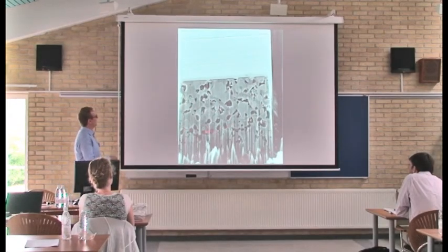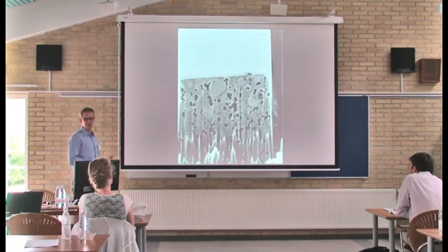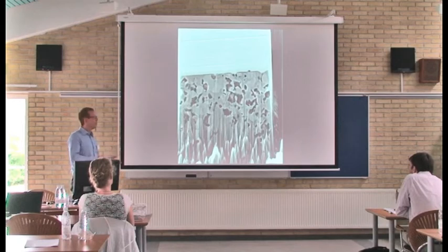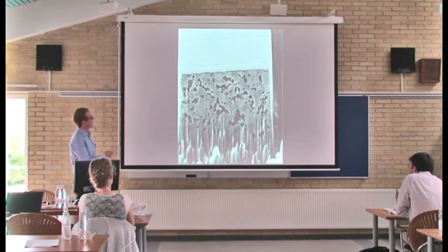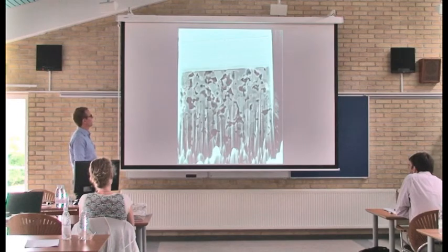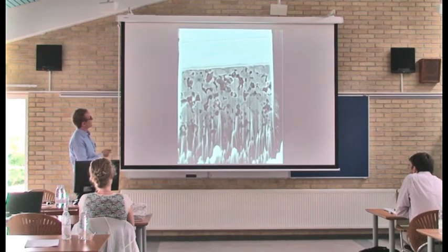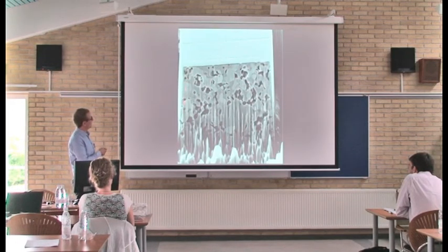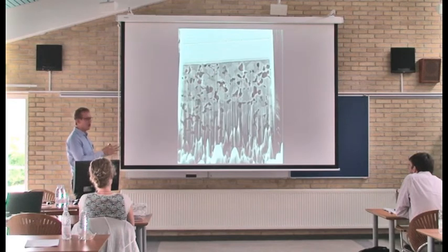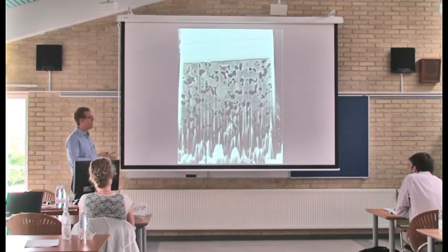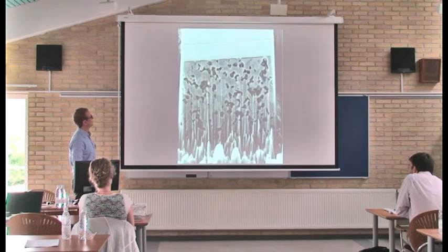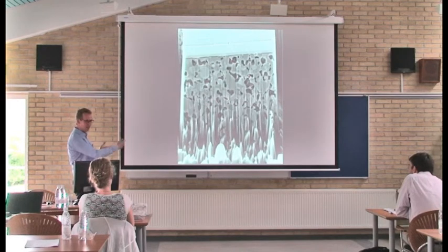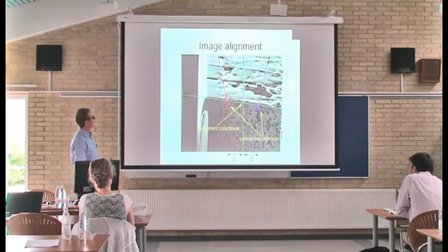This is the kind of data you get out of, for instance, focused ion beam tomography. It's a video of a data session where each frame is one frame from the image acquisition process. Due to the geometry of the focused ion beam setup, the rectangular region that you want to cut out to produce a cuboid of data for further analysis actually moves upwards in the image. You can also see a bit of a shift, where the whole sample moves a bit to the right in the image. So we want to correct for this.